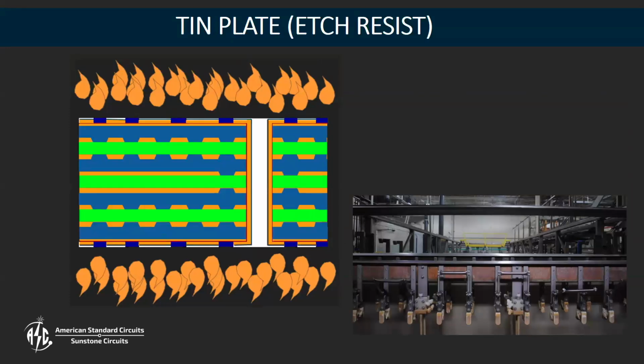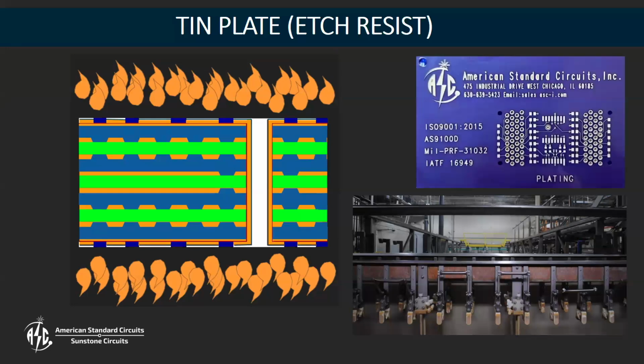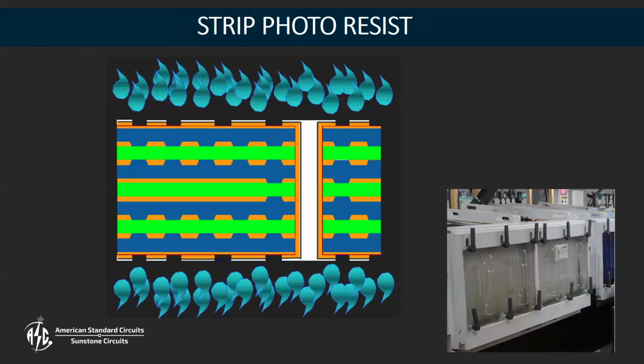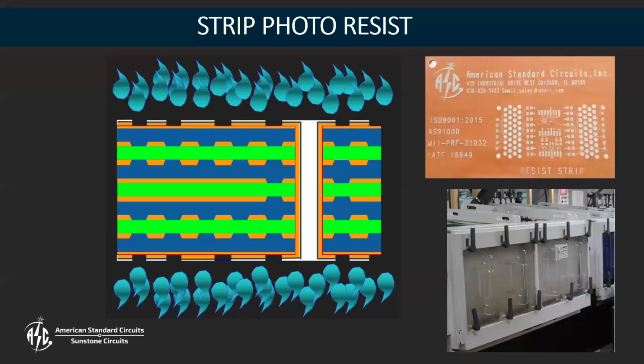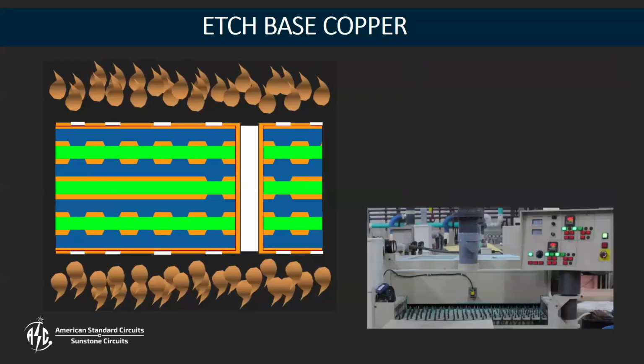So, all right, after the copper plate, we electroplate a little bit of tin onto the surface of all of that copper, and this metal is going to act as our etch resist through our etching process in the next step. So before we used photoresist, now we're going to use tin as an etch resist. Okay, so we got tin plated on top of our copper through holes and pads. We're going to strip off our photoresist at this point, exposing the copper below it that we want to remove. Okay, there's our exposed copper and our tin.